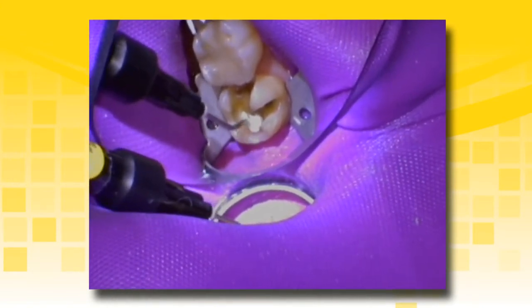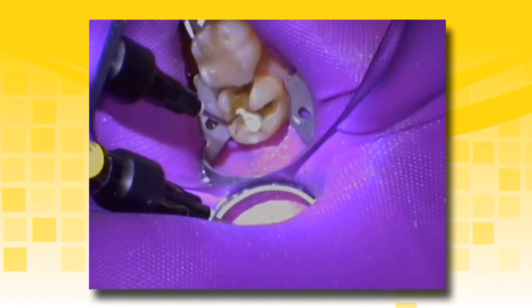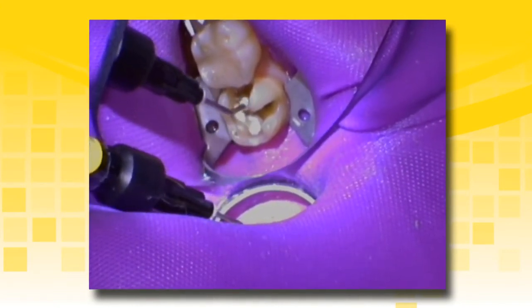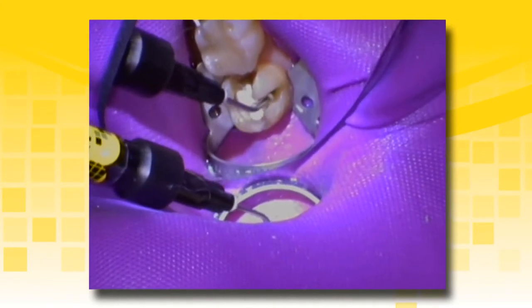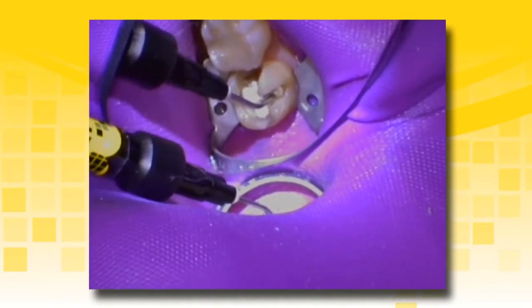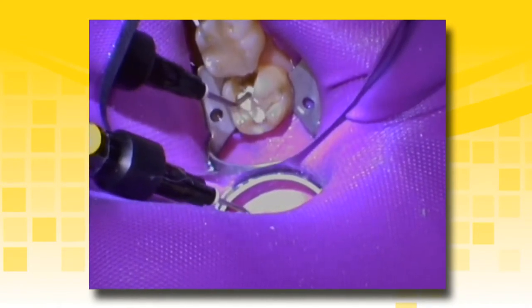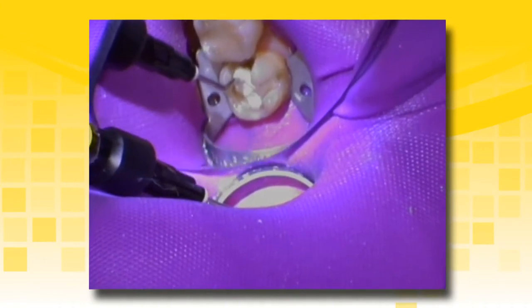The layer should not exceed 1 mm in depth to ensure adequate cure. Manipulate the material into a smooth surface covering all deep dentin areas. Use the tip or ball end hand instrument to move the material where it is desired. TheraCal LC will stay where you put it, even on vertical pulpal axial walls. If using multiple layers, light cure between each layer. After curing for 20 seconds, the completed liner should have a smooth surface that is ready for an adhesive.